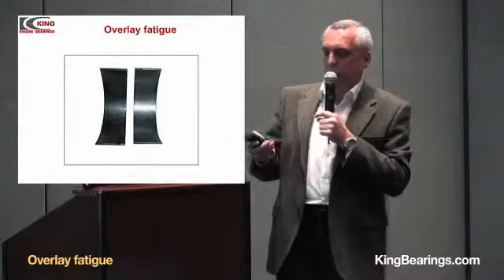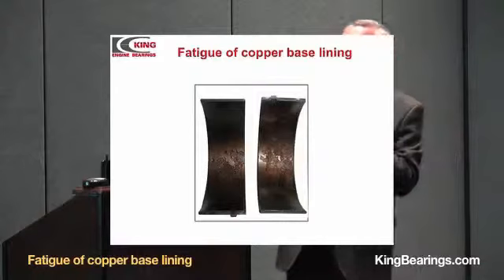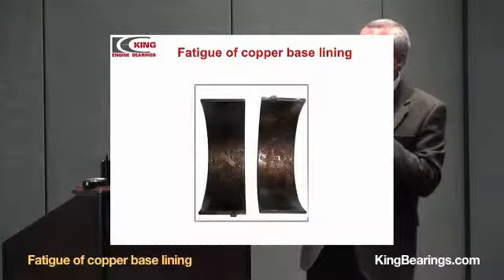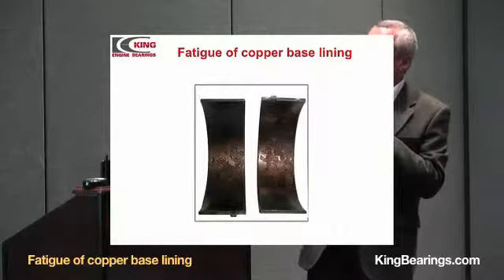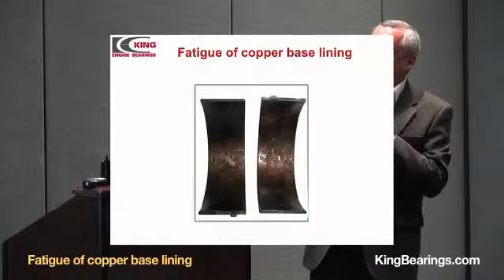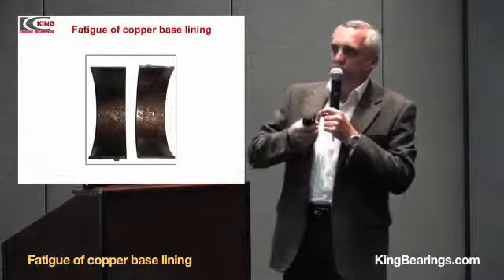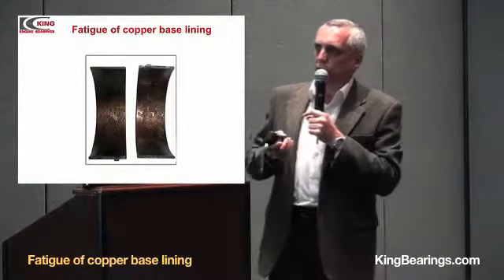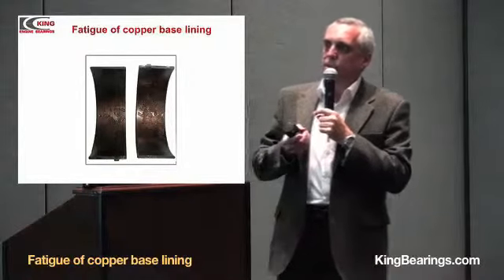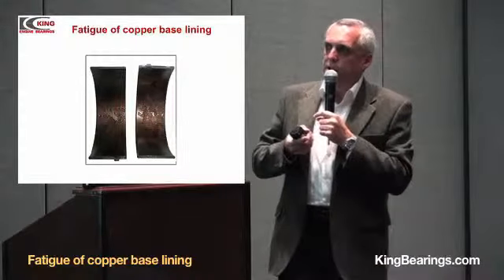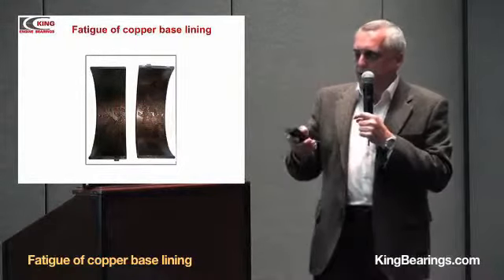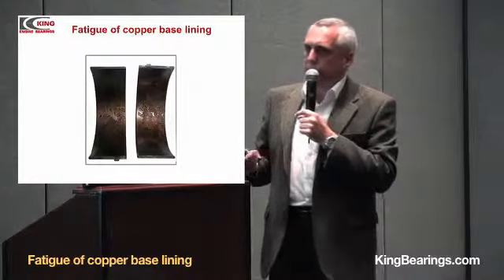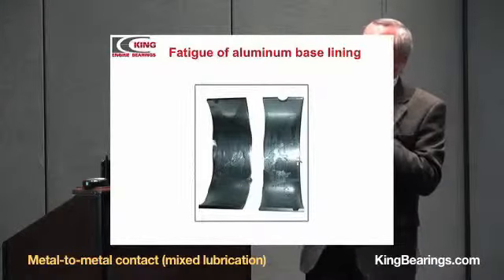If there is a fatigue of copper-based like this, it looks like cratering on the surface. You see craters, particles of the copper-based intermediate are delaminated from the surface. It is very bad. It is catastrophic failure. The same aluminum.